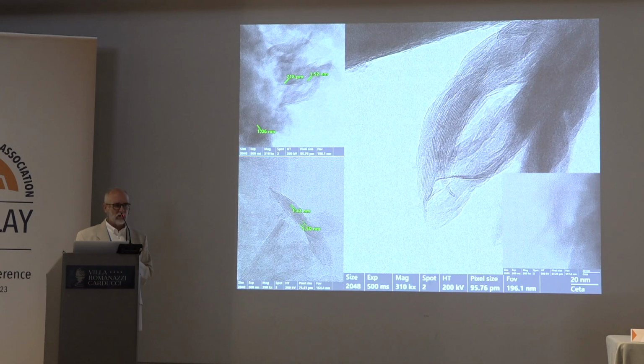In transmission, we prepare the sample in 2 ways. We want to go deeper in the scale. So we prepare sample on copper grid, so it's some different areas ground, intensively ground, and deposit on the grid. But also we prepare the sample in resin, and we prepare the ultra thin sections.